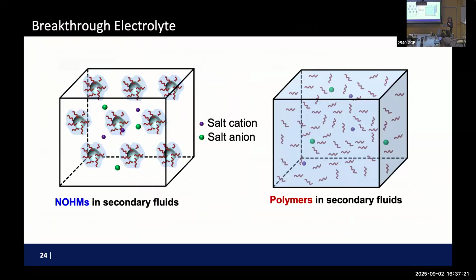So let's think about a very simple system. Two fluid system. One is with the NOHMs, the other one with the polymer, which is untethered. So this is tethered, same polymer here, same polymer here. The major difference is that this one has nanoparticles, this one doesn't. The polymer here is untethered, this one is more structured, bound to the surface. That's the only difference. So looking at that, I thought, if this solution behaves as well as this, close to that, as electrolyte during the CO2 reduction, I would love it. Because having all these nanoparticles, inorganic materials, I thought this should have a higher viscosity and lower conductivity. That kind of makes sense, right?